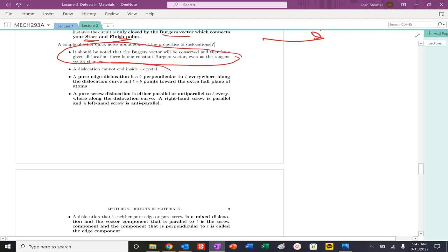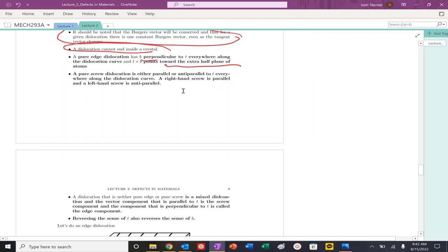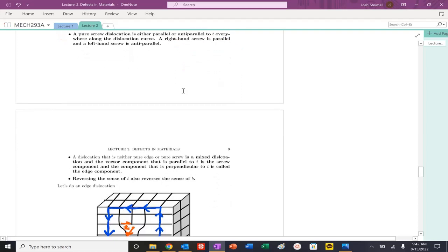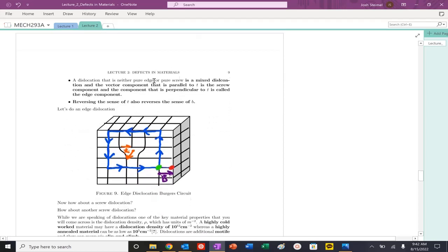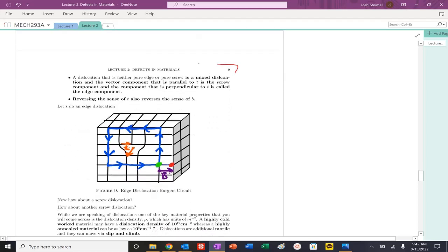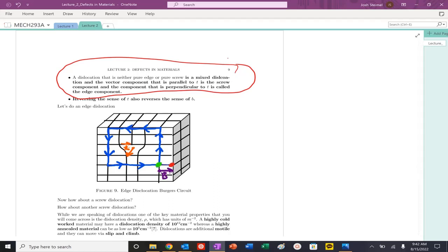It doesn't matter how you choose your tangent vectors. A dislocation cannot end inside a crystal. Once you complete this circuit, if your Burgers vector is perpendicular to your tangent vector, this T cross B points to the extra half plane. That will be an edge dislocation. If you have a screw, if it's parallel to the tangent vector, it's going to be right-hand screw. If it's anti-parallel, it's left-hand screw. You can also have a mixed dislocation. In reality, in materials, you're going to have mixed dislocations. Some parts will be edge, some parts will be screw, some parts will be left-hand screw. There will be some components of both. We are going to focus on the pure examples here in this course.